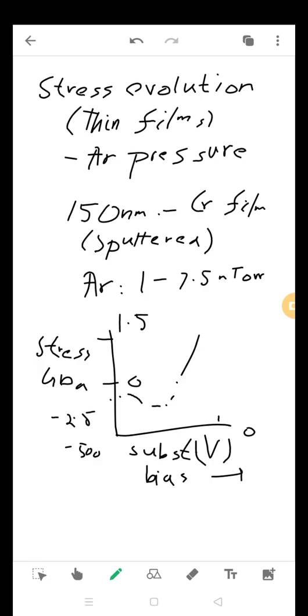So there is a transition zone. Below that it is compressive, and above that it is tensile. So the transition takes place between the nature of the stress as we move from minus 500 volts to 0 substrate bias. Now, what we observe is that there is a residual stress.